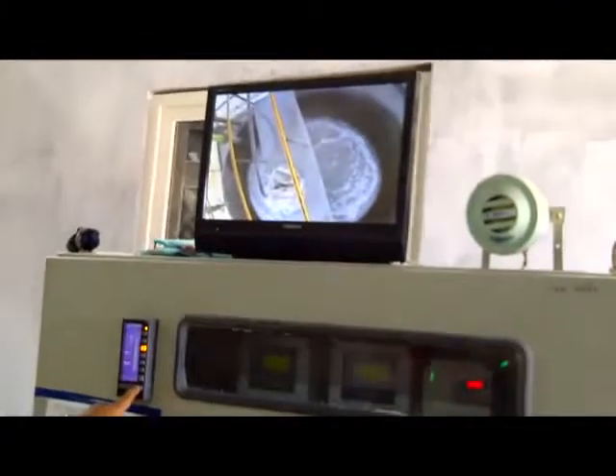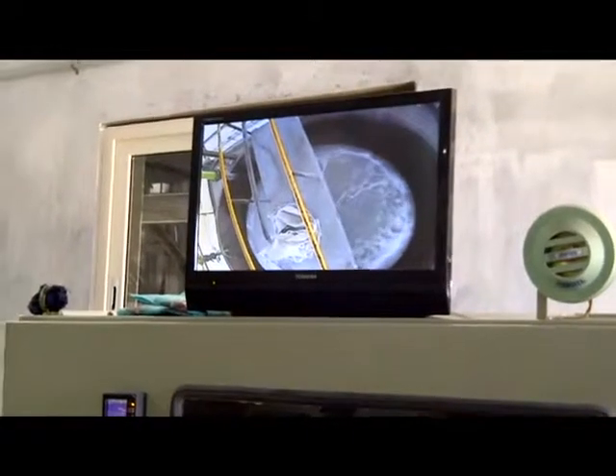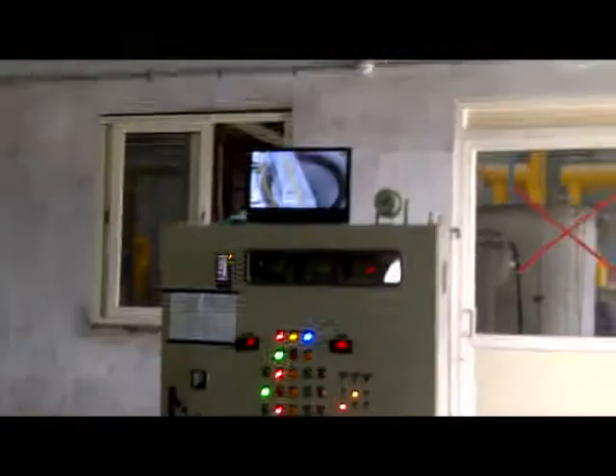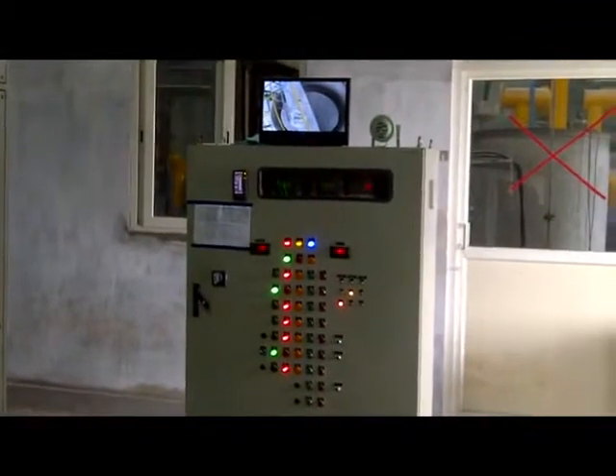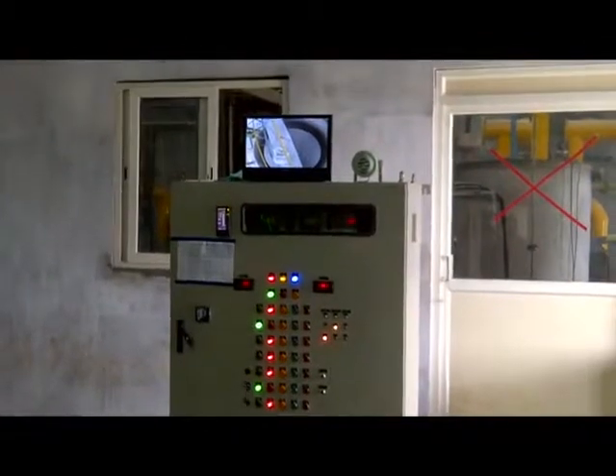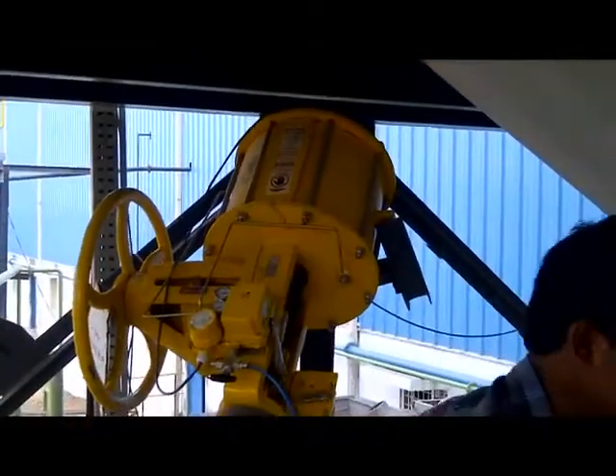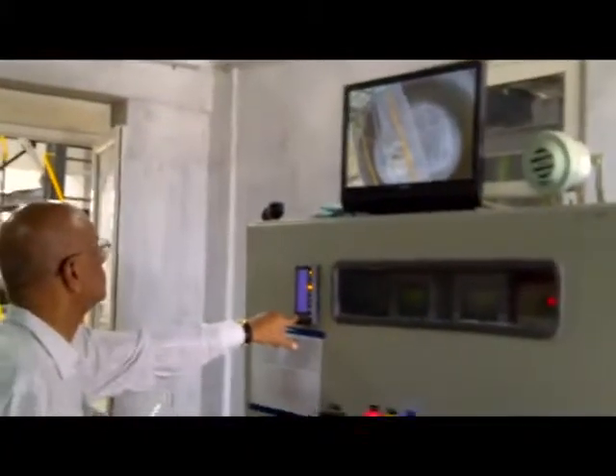It is essential to have a stable interface of froth and slurry in the flotation column for effective separation and control over the product quality and recovery. The interface is maintained and monitored by a differential pressure transmitter and a discharge valve in a control loop through a process controller. Bubble generation system is the heart of the column flotation technology.